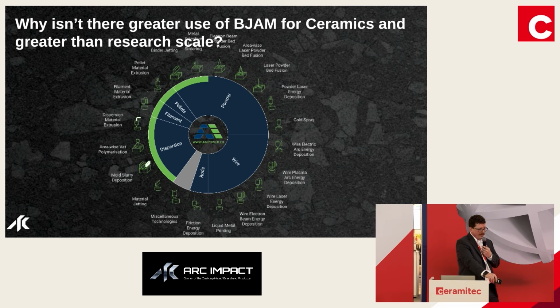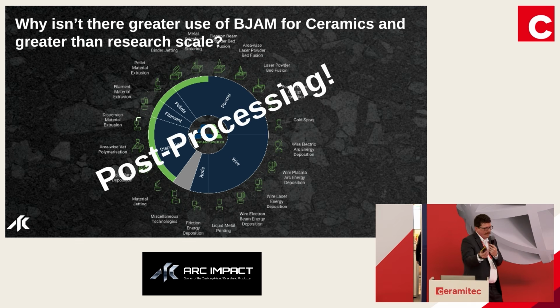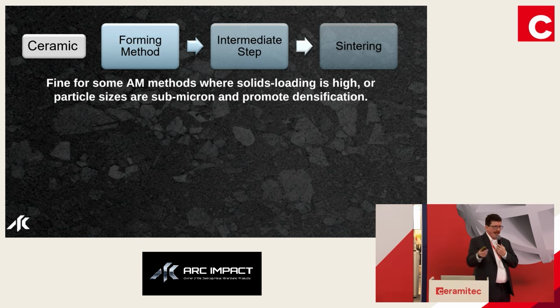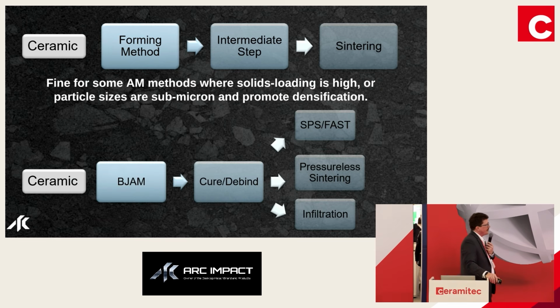So why aren't we seeing much more beyond this sort of siliconized silicon carbide space? And why aren't we seeing that really beyond the research scale? It's the post-processing. It's what do you have to do with the parts once you have them out of the curing oven? How do you take that to a finished product? In some of these other additive techniques, where you either have very high solids loading because you have a paste where you can jam a bunch of particles in there, or have very high concentration of submicron particles that promote densification, you can directly sinter. It might take a couple days to densify, but you can encourage that. But on the binder jetting side, you're currently particle limited by what those particle sizes are and what's printable. So you have to look at other techniques.